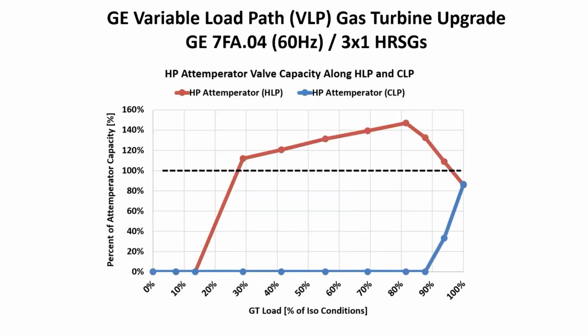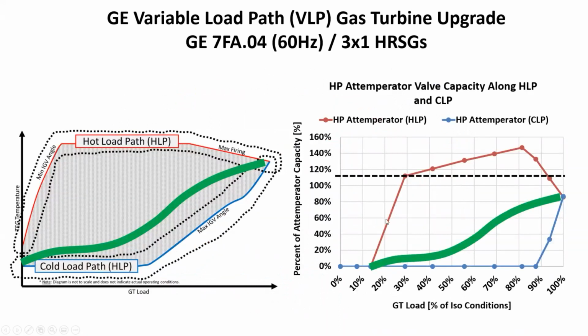And it definitely has some effects. This is one example showing the difference between attemperator spray water capacities along the hot load path and along the cold load path. If you look at them side by side, the hot load path causes the HP attemperator to reach its capacity very rapidly, while on the cold load path, the gas turbine load reaches 90% before any spray water flow is required. If you imagine some intermediate path, you might have some higher degree of attemperator spray water flow rates reaching capacity. However, if you follow this cold load path most of the way up to base load conditions, it's quite possible that you're going to see lower spray water flow rates than you would at typical operation.